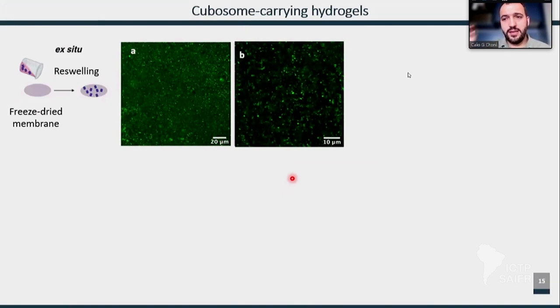The point is that they are small, tiny particles, not that tiny. I mean, 200, 300 nanometers, but they're still tiny. And we try to incorporate them into polymer membranes, wet membranes. And these membranes have a mesh size much larger than the particles. So we can incorporate, you can see that by the fluorescence, that whatever is fluorescent here is the cubosome with a fluorescent dye.